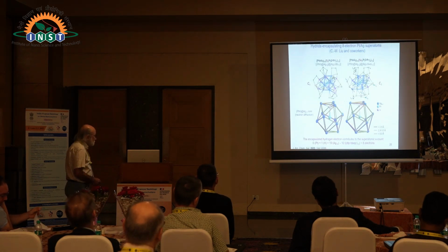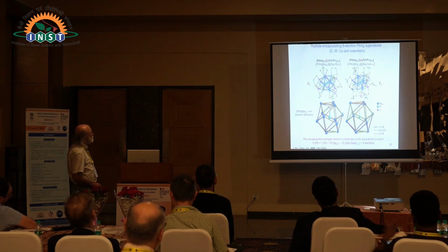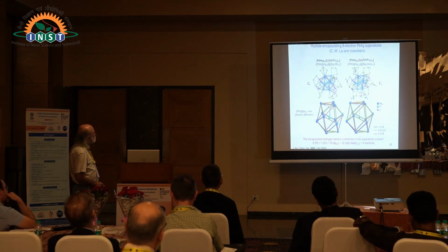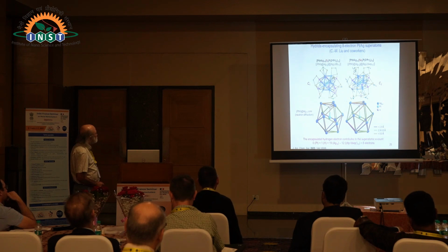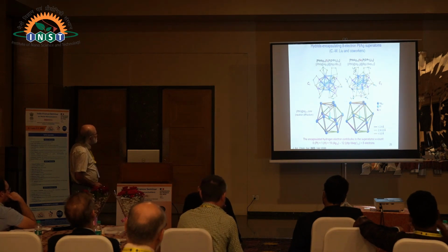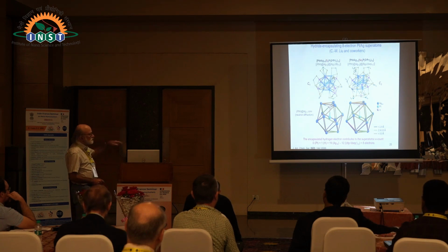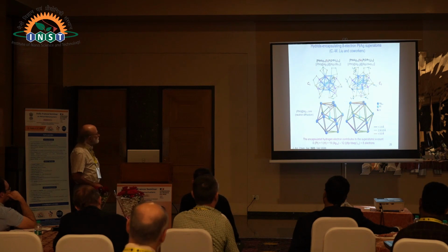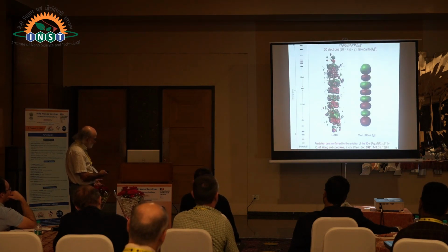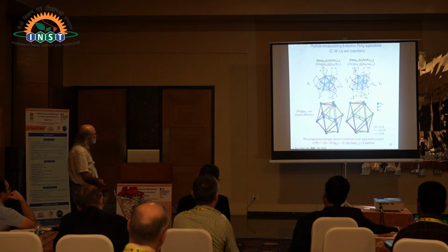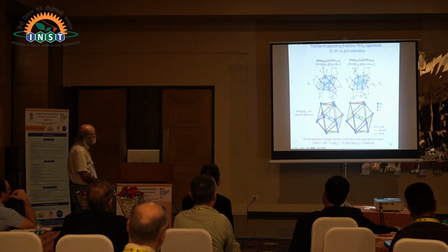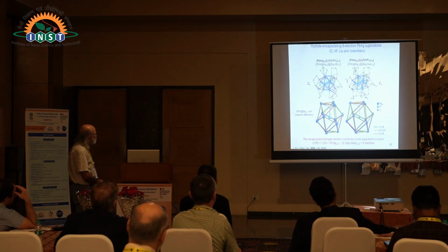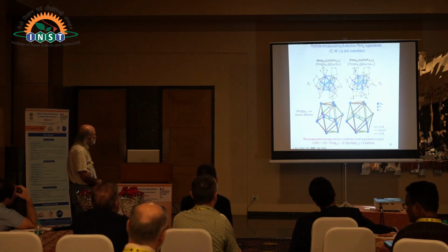Now I would like to shift to something which we are interested in at the present time, still made in the group of Liu. These two compounds, this is sulfur, this is selenium, this is C1, this is C3, two different protecting shells, and there is a neutron diffraction structure. But what is interesting is that they contain a hydrogen encapsulated within the icosahedron. Actually, the hydrogen is strongly bonded to platinum, which is at the center, and weakly to the copper atoms.